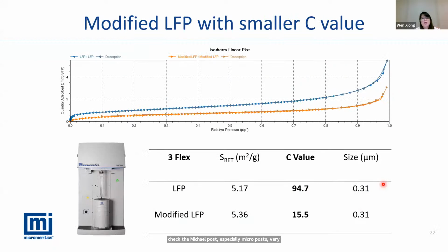Here is an example of using 3Flex to determine very tiny differences, in this case the surface modification of lithium iron phosphate materials. We were doing the surface modification by ALD, atomic layer deposition, on the surface. From the isotherm, we see the specific surface area of the lithium iron phosphate only changes